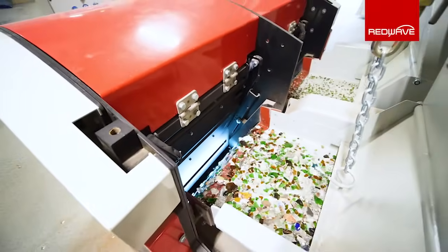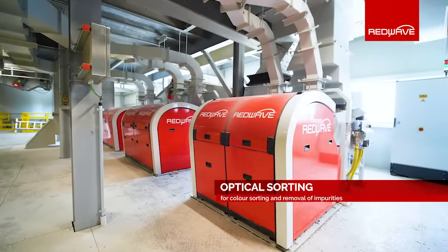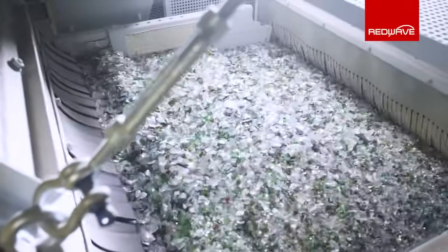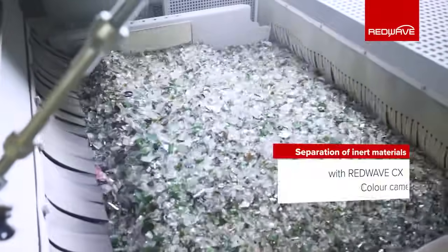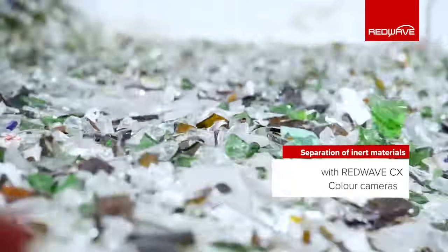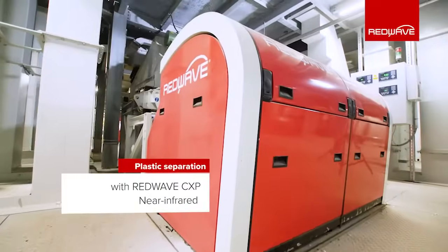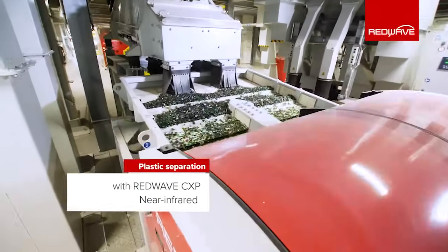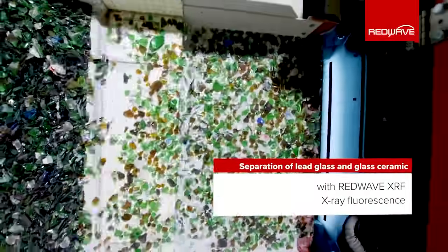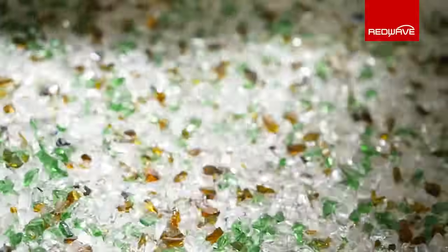At the subsequent optical sorting process, the glass — which is now called cullet — is cleared from plastics and other inert materials by RedWave sorters with different sensor configurations. Color cameras search the cullet for inert materials such as ceramics and stones, whilst plastics are recognized by the means of near-infrared spectroscopy sensors. Glass with traces of heavy metals such as lead glass and glass ceramics are detected by X-ray fluorescence technology. Upon detection, unwanted materials are rejected by air valves.